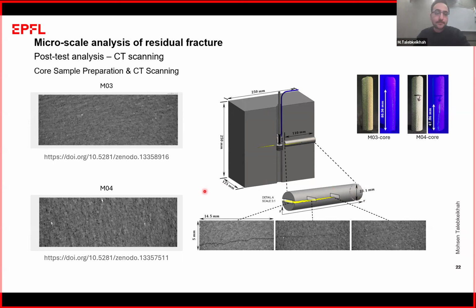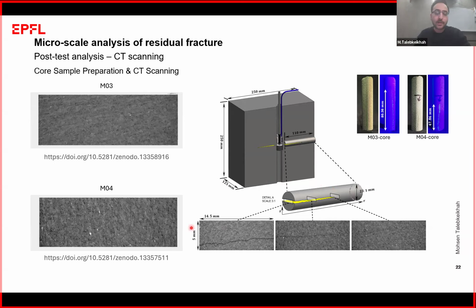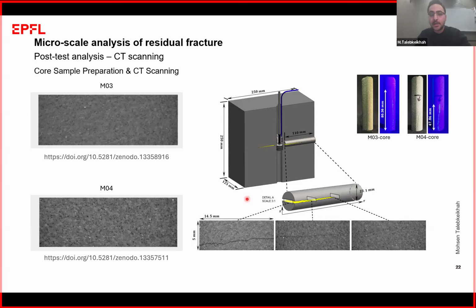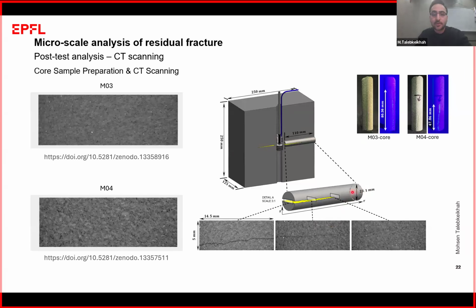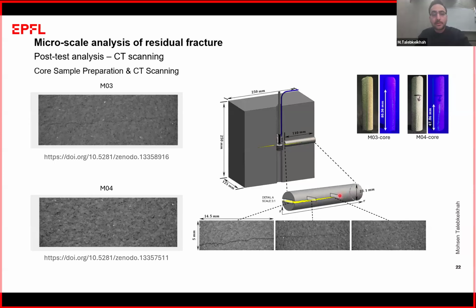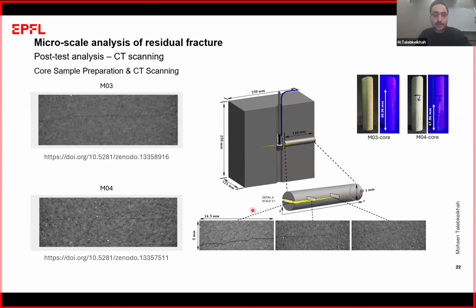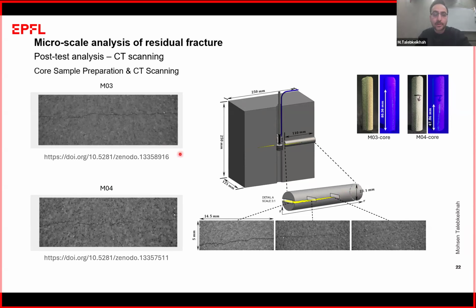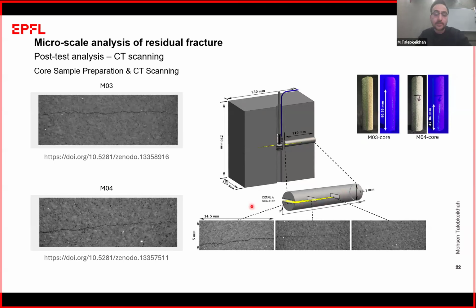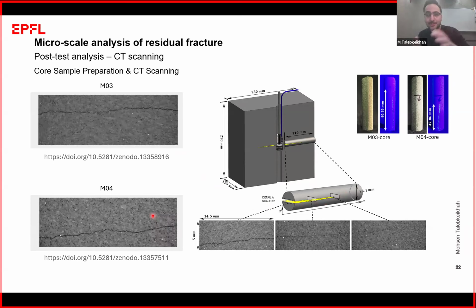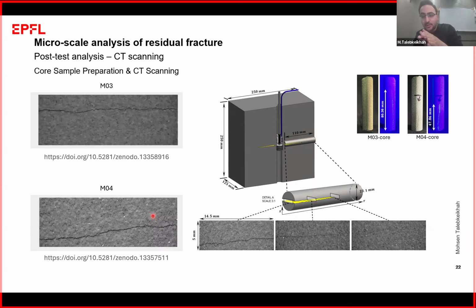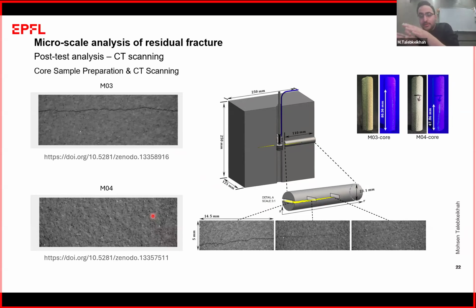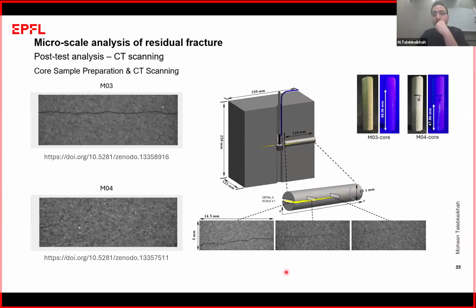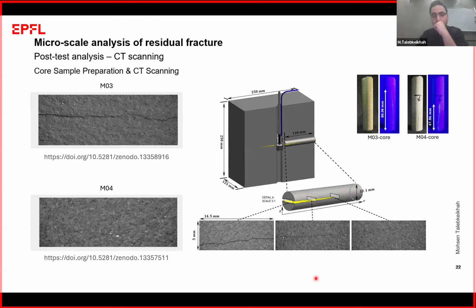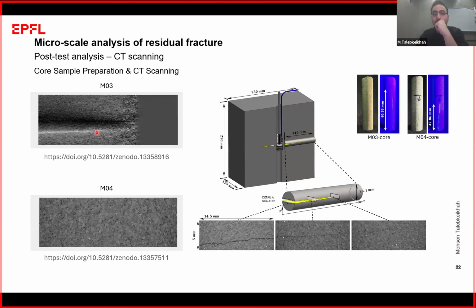Here you can see for both experiments that the CT scan goes and reaches the tip of the fracture, and as it gets closer to the inlet of the fracture, the fracture size and the residual opening increase and increase. At the end you can also see the notch here.